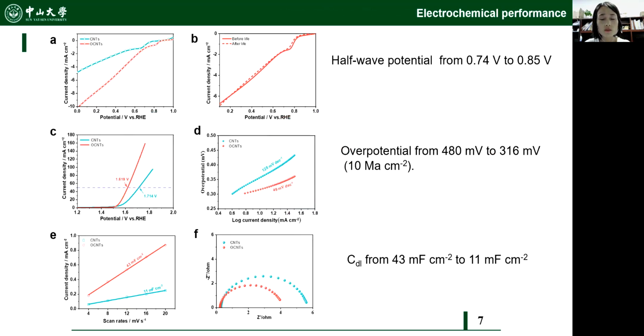The ORR and OER performance was evaluated. The ORR catalytic performance of OCNTs is boosted, as demonstrated by its significantly higher onset potential and half-wave potential in contrast to those of CNTs. Likewise, it also possesses better catalytic activities towards OER than the CNTs, exhibiting a low overpotential of 316 millivolts at 10 milliamperes per square centimeter and a smaller Tafel slope. The active surface area of OCNTs is also remarkably superior to CNTs.